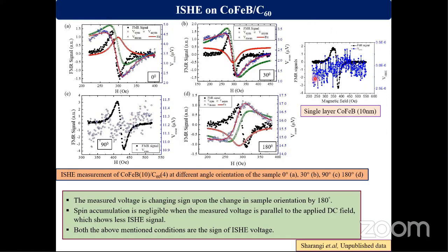So we have also performed the ISHE measurement on the single layer cobalt iron boron sample, but for the single layer cobalt iron boron sample, we did not get any ISHE signal.